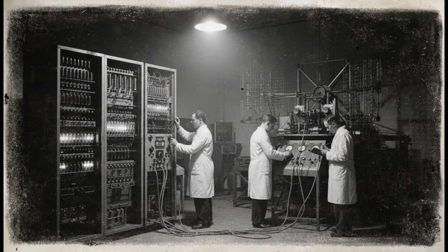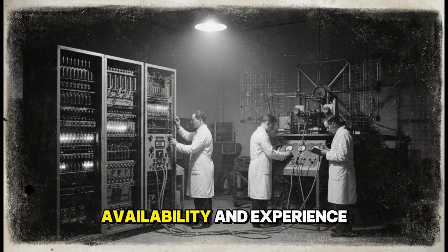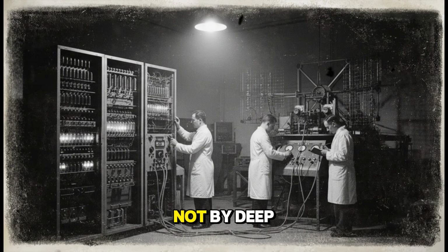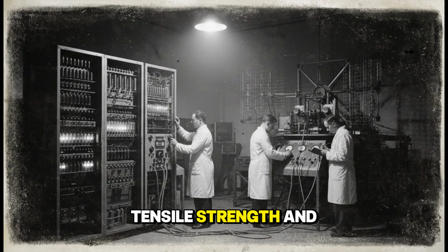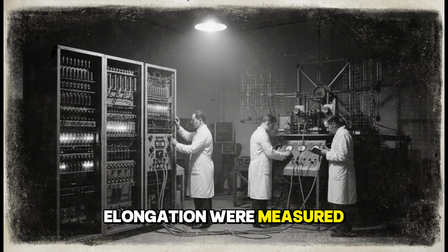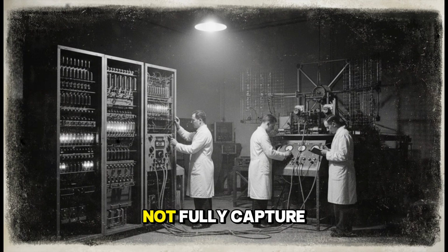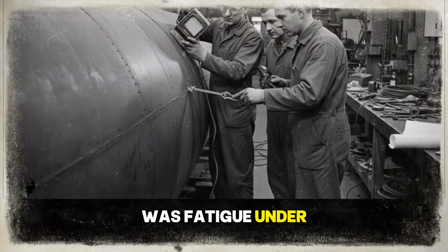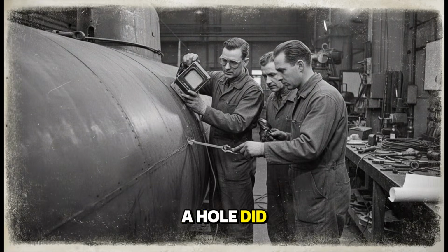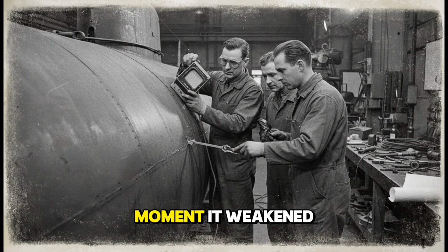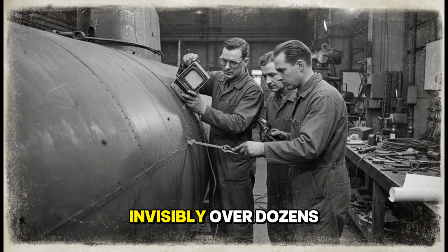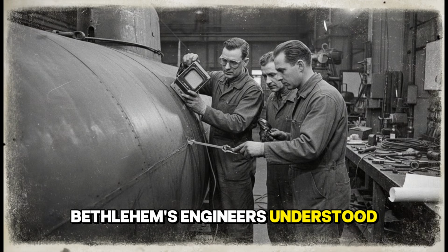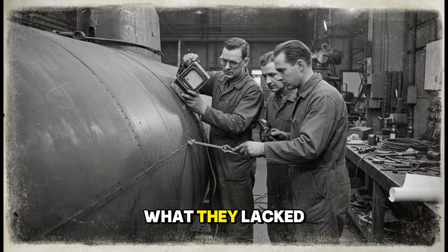Before the war, American standards had been shaped by availability and experience, not by deep ocean physics. Yield strength, tensile strength, and elongation were measured in isolation. What they did not fully capture was fatigue under cyclic pressure. A hull did not fail in one dramatic moment. It weakened invisibly over dozens of dives. Bethlehem's engineers understood this intellectually. What they lacked was a proven method to change it.